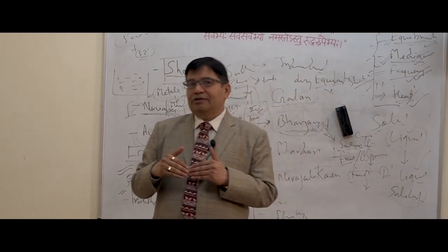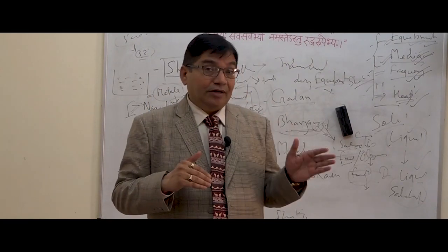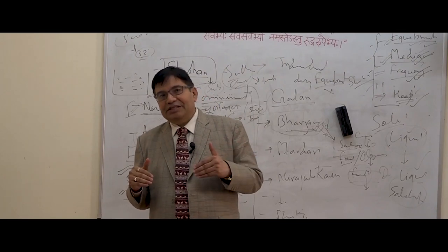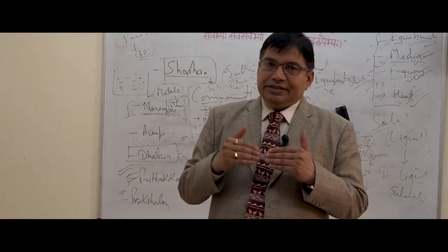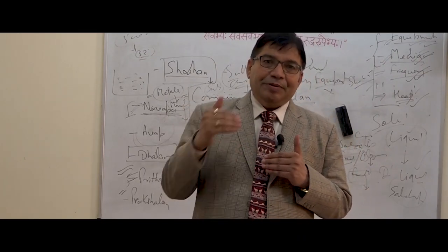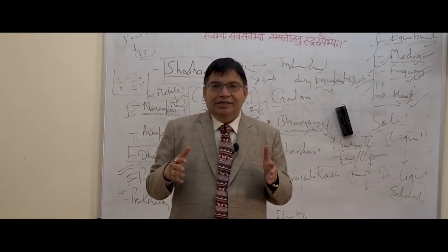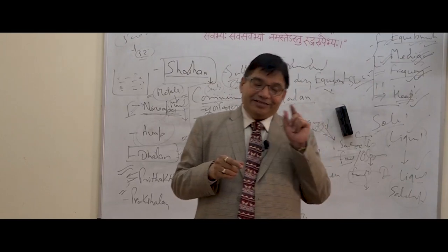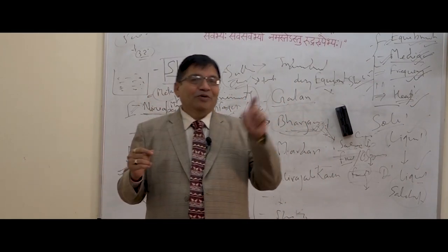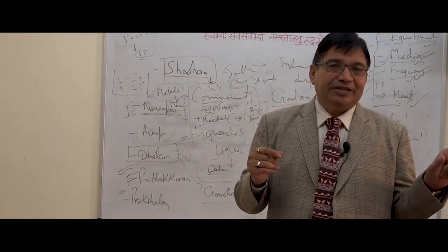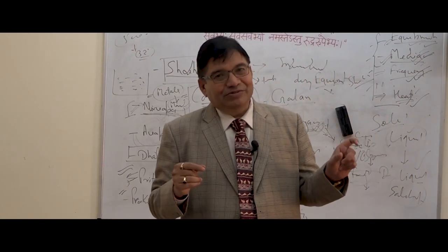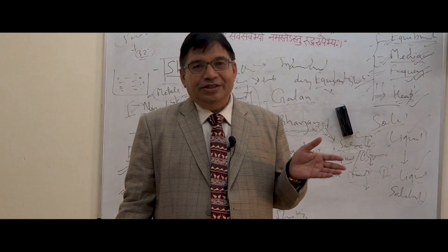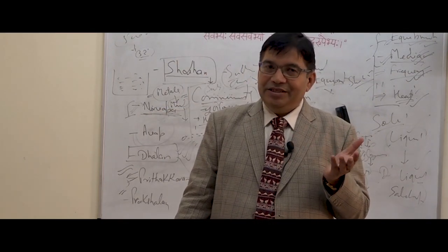And the bhasma of both were prepared. Then the bhasma prepared with the copper powder quenched in plain water, and the bhasma prepared after the routine normal shodhan, were given to the rats. The normal tamrabhasma prepared by applying the methods of the Shodhan and the Maran as per the classics of the Rasa Shastra was not showing any toxicity, whereas the other tamrabhasma got the same black color in the process of the Maran, but it was not purified as per the classics of the Rasa Shastra. It was just quenched 35 times in water. All the experimental rats given that tamrabhasma, prepared without following the method of the Shodhan, had a lot of kinds of anomalies in their vital organs.